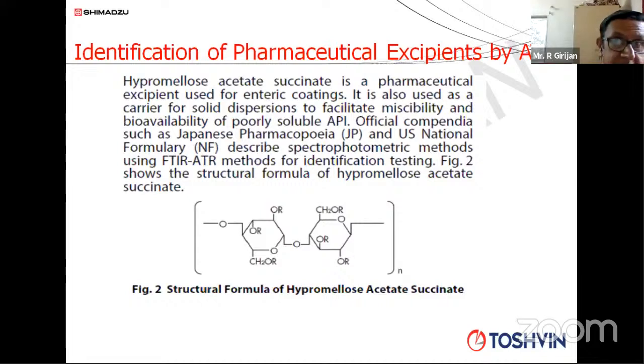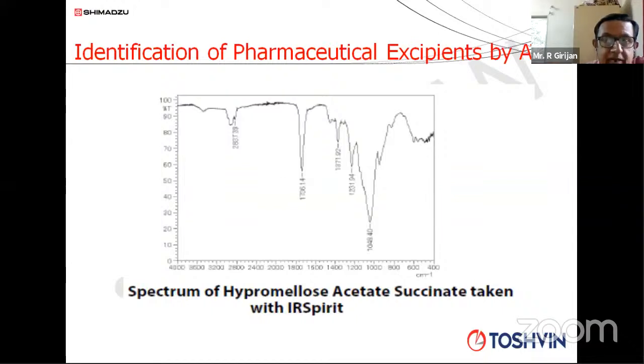Hypromellose acetate succinate is a very prominent pharmaceutical excipient used for enteric coatings. It is also used as a carrier for solid dispersions to facilitate miscibility and bioavailability of poorly soluble API. Official compendia such as the Japanese Pharmacopoeia and the US National Formulary (NF) describe the qualitative identification of this material by FTIR with the ATR technique. You can see the structure of hypromellose acetate succinate, and we have analyzed it by normal ATR, diamond ATR, and you can get the spectrum and identify the compound.